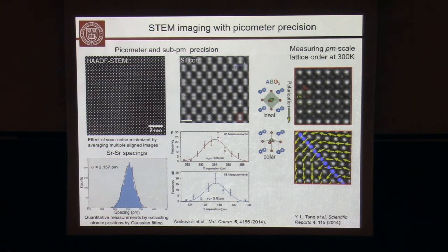What can we do with this? Here's an example from the group of Ramesh, who has demonstrated that by measuring the position of each atom and extracting the polar displacement, you can actually discover polar displacement vortices, this vortex antivortex pair, in strontium titanate, lead titanate superlattice. So you discover new phases by being able to actually track atoms at that scale.